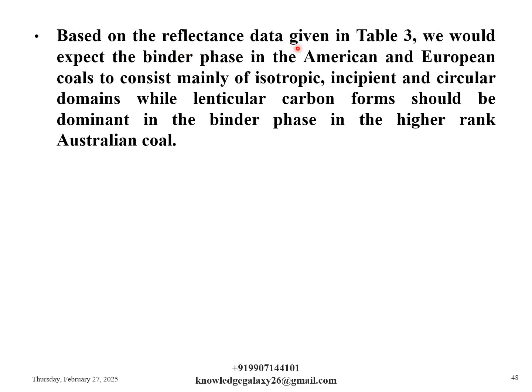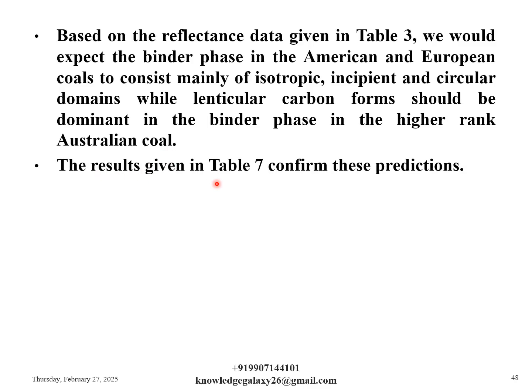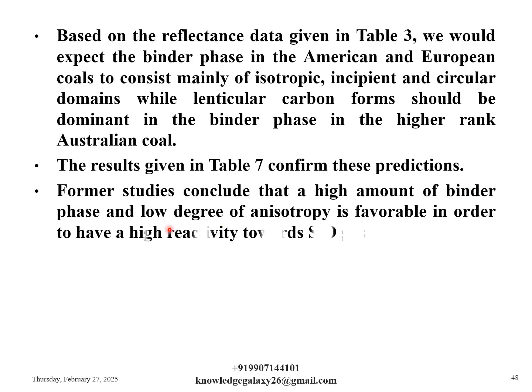Based on the reflectance data given in table 3, we would expect the binder phase in the American and European coals to consist mainly of isotropic, incipient and circular domains, while lenticular carbon forms should be dominant in the binder phase in the higher rank Australian coal. The results given in table 7 confirm these predictions. Former studies conclude that a high amount of binder phase and low degree of anisotropy is favorable in order to have a high reactivity towards SiO gas.